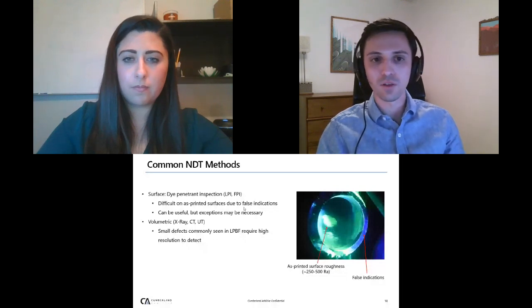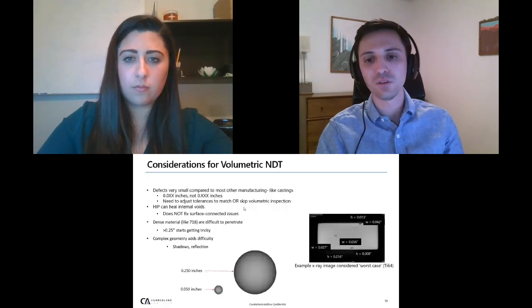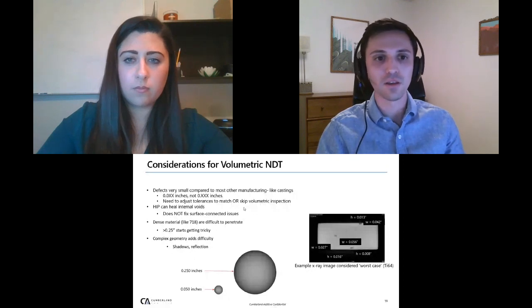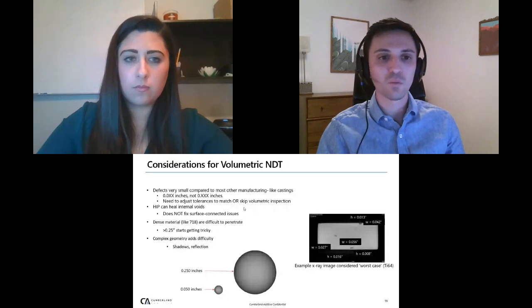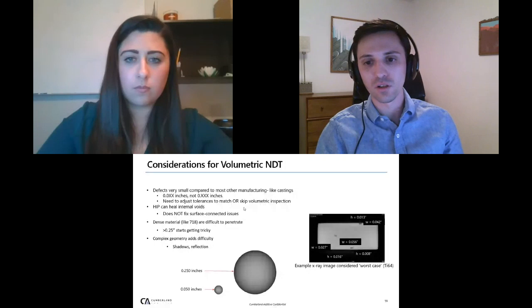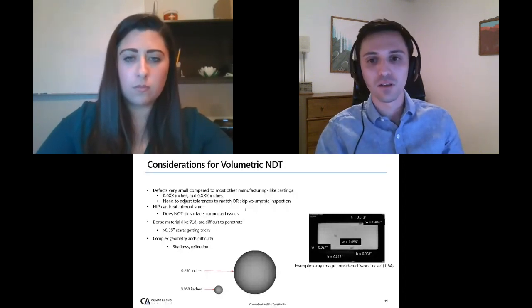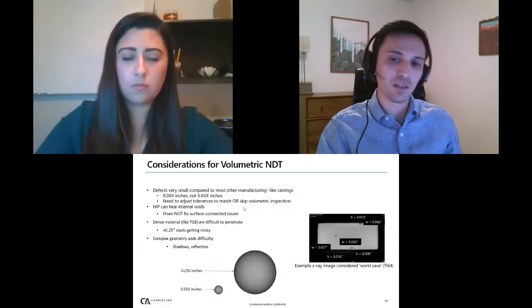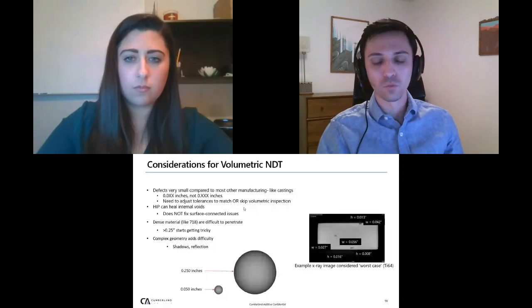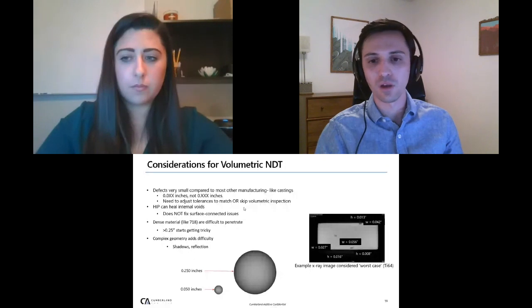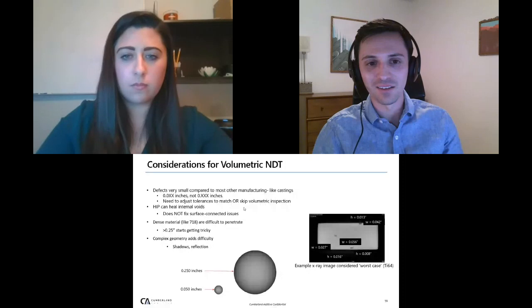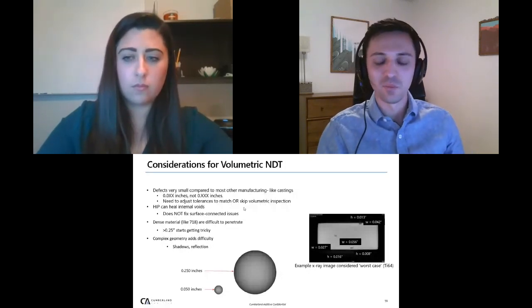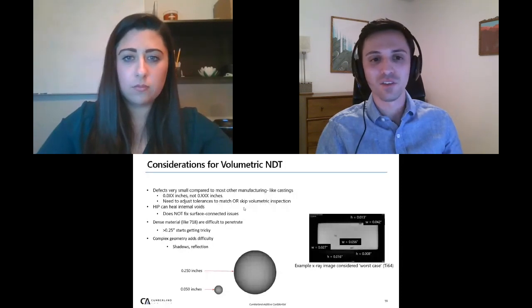So volumetric is the other kind of major category of NDT that's commonly used in AM. That's ultrasonic, CT, X-ray. The types of defects you'd be looking for are really, really small, on the order of not tenths of an inch, but hundredths of an inch. The worst case is an image on the right there where we found an indication of 56 thousandths of an inch. That's, in my book, really, really bad for us. And yet it was being compared against a spec that was looking for 1/4 inch voids. So really, really nasty voids that you might get in certain casting processes. So if your spec is looking for something of that general scale, maybe you just skip volumetric. Yeah. So HIP can heal all these things unless they're surface connected. If the pore goes to your surface, then HIP won't do anything for you.